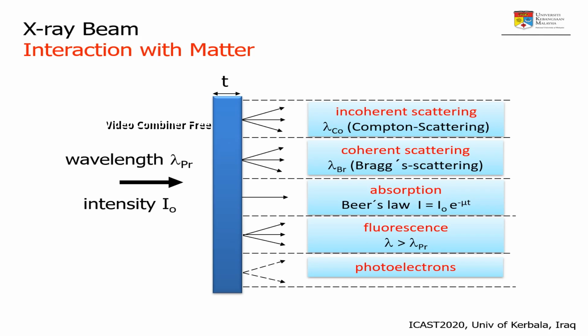When absorption occurs, the X-ray interacts with the material at the atomic level, causing fluorescence, which forms the basis of X-ray fluorescence spectroscopy. The X-ray can also be scattered from the material. The scattering can occur either with the loss of energy or without, known as Compton and Rayleigh scatterings respectively. The ratio between absorption, fluorescence, the two scatterings, as well as transmission, depends on four main factors, namely sample thickness, density, elemental composition, and the X-ray energy.